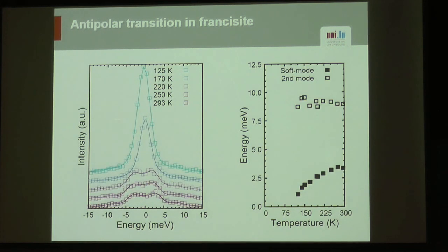Then obviously we want to do that with temperature, so this is what it looks like. Room temperature is here at the bottom, so it's still quite weak, and as you approach the transition, it goes down in energy and up in intensity. When you fit this with the classical damped harmonic oscillator model, you will find this kind of soft mode behavior.